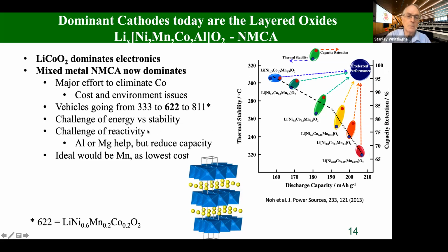So one of the means of addressing the reactivity is a little bit of aluminum, magnesium helps. It makes a 10 or 20 degrees centigrade improvement, but it reduces the capacity. Manganese is much more thermodynamically stable and it's lower cost, but its rate capability today is not good.